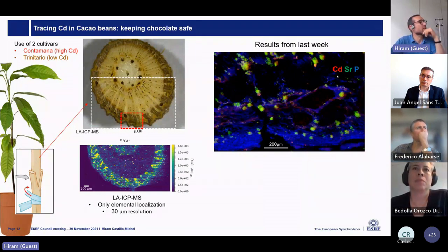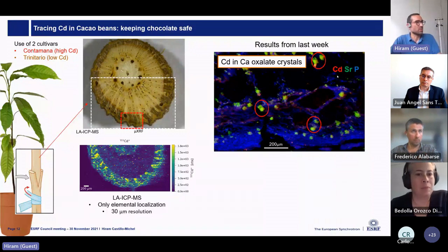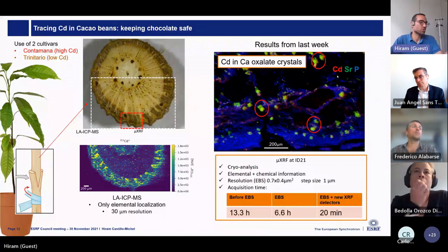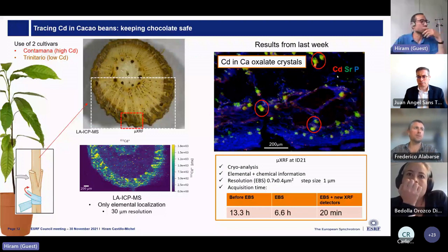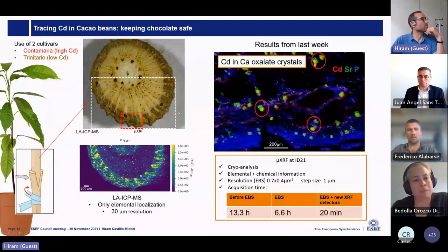There are a lot of these crystals in the branches, which are actually the main location of cadmium, which is a happy result, which means that we could get even more cadmium in the beans if these crystals in the branch were not capable of actually retaining most of the cadmium which is being absorbed. So cadmium is in the calcium oxalate crystals. And also, just to give a context again, we are trying to push this acquisition. For the time being, we are at about 6 hours to give you a map like this. But with the new detectors and with a decrease by a factor of 20, you will get this image in 20 minutes, or we can approximate our area of analysis to what we can do in laser ablation ICP-MS, but with much better resolution.